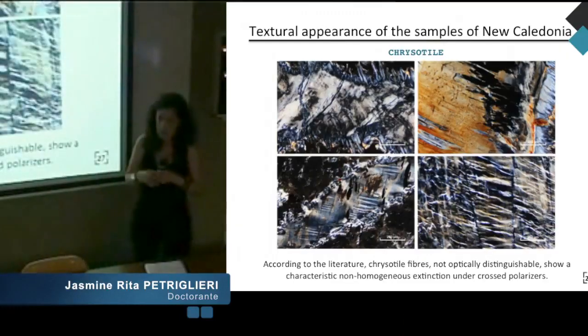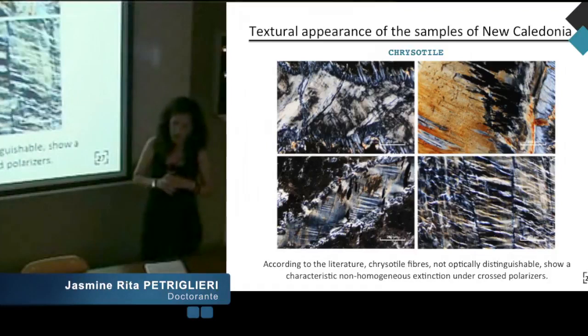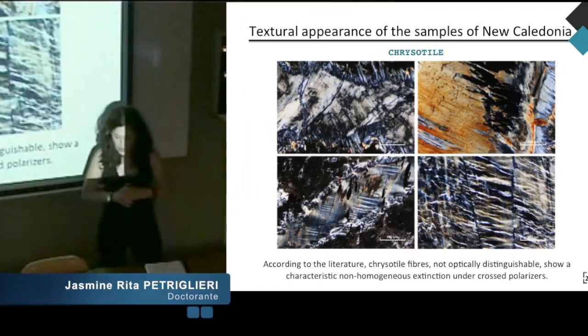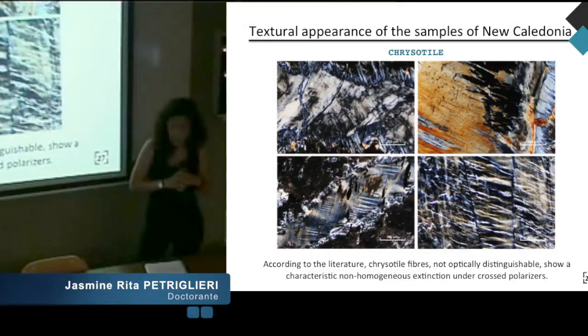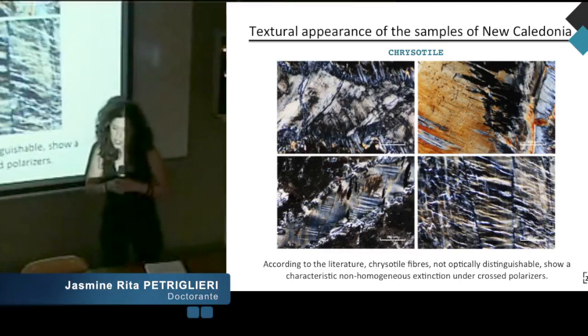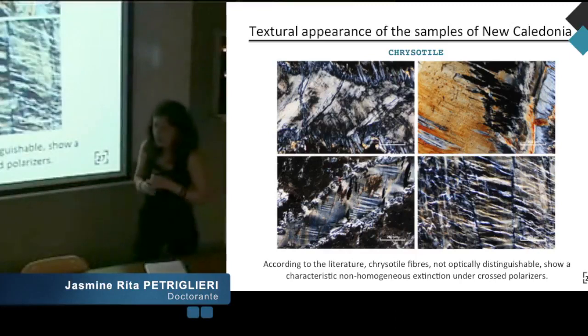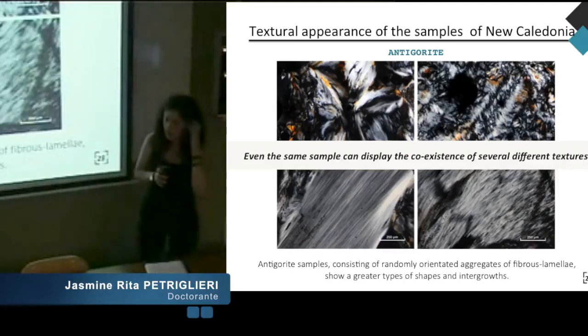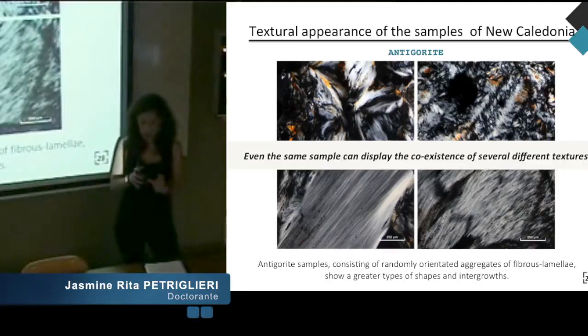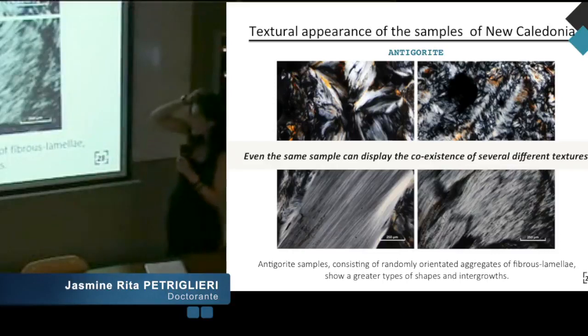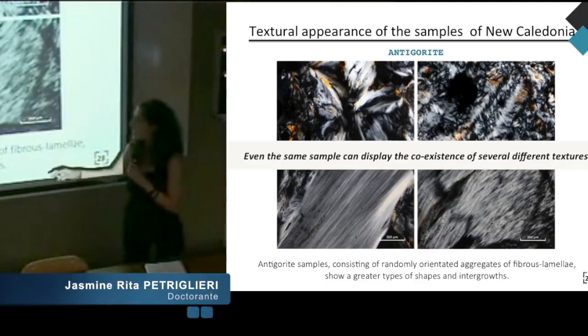In this context, we decided to study in more detail the textural and morphological appearance of the samples of New Caledonia. Concerning chrysotile, optical microscope images show the typical characteristic image found in the literature. On the contrary, antigorite samples in New Caledonia consist of randomly oriented aggregates of fibrous lamellae that show a greater variety of shapes and intergrowths. We can observe in the picture 4 kinds of texture, from left to right: star and fan-formed aggregates, the most typical interpenetrating texture, lath-shaped lamellae, and the fibrous blades.